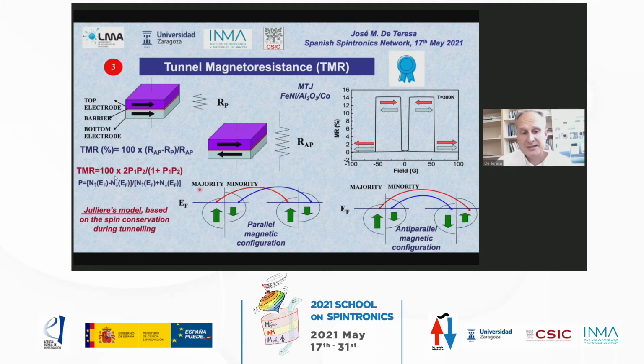Okay, so by doing the calculation of the current in these two configurations, you obtain that it can be expressed just by the available density of states in the first electrode and the available density of states of the second electrode. And you can express it as a function of this spin polarization, the difference between the density of states in the spin up and the spin down subbands. So if you have a material with a high spin polarization, you will observe a high tunneling magnetoresistance. This is the model of Julliere that is based just on the spin conservation during tunneling.